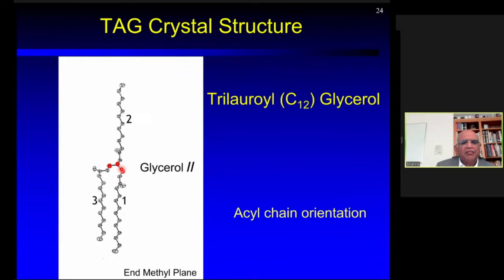The glycerol carbons are indicated here in red, 1, 2, and 3. And the acyl chain at 1 goes down, and the acyl chain at 2 goes up in a straight line between 1 and 2. And the 3 acyl chain bends at the carbonyl and packs along the side of the 1. So when these 1 and 3 chains are packed together, the glycerol carbon axis or orientation is parallel to the methyl plane. So that is what happens when 1 and 3 chains are packed together.